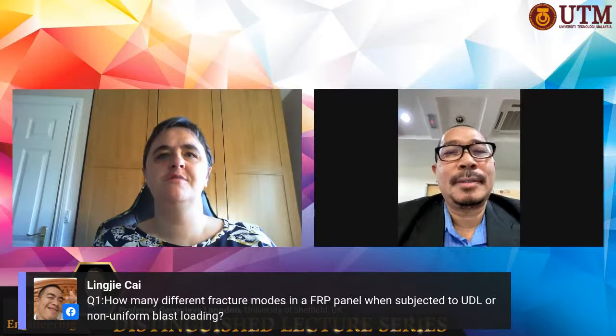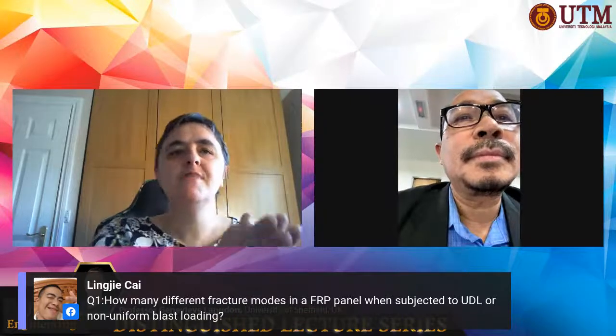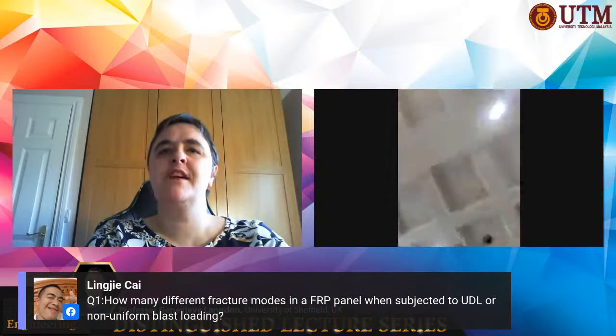How many different fracture modes in FRP panel when subjected to uniformly distributed load or non-uniform distributed load? Okay, so in a non-uniformly distributed load, you're much more likely to see localized fiber fracture and shearing. In a uniformly distributed load, you tend to get those failures located at the boundaries. So it's not so much that you see different fracture modes, it's more that they occur in different places for different reasons.